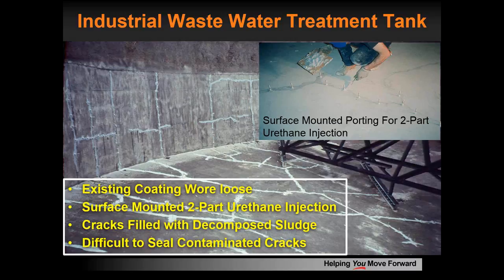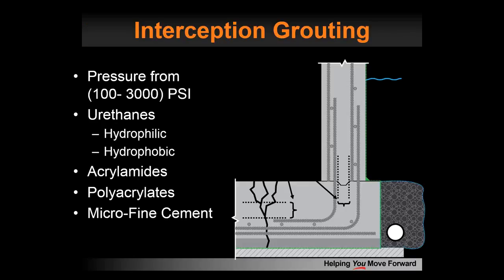Now at the bottom there, I note it's difficult to seal contaminated cracks. Many times in these wastewater tanks, there's a lot of sludge and debris in the cracks, so you do not always get 100% seals. Normally, if you can get 90% or better, you're doing pretty good.